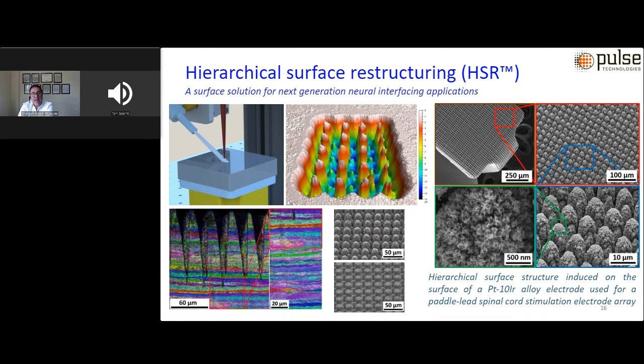So right there, that confocal image that I'm showing, it shows the unrestructured surface of an electrode, which is kind of the whitish gray area, and then it shows the restructured area. So you could see that there is some degree of material removal or ablation, in the order of a few microns from the surface. Therefore, if the electrode is extremely thin, there might be some limitations.